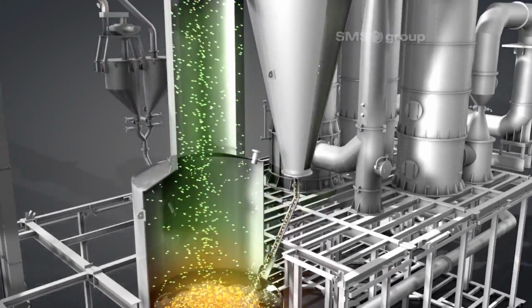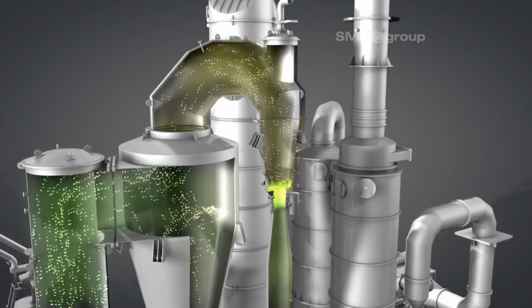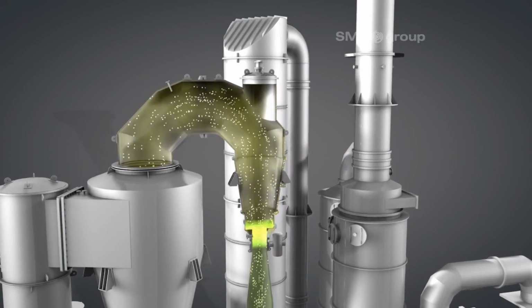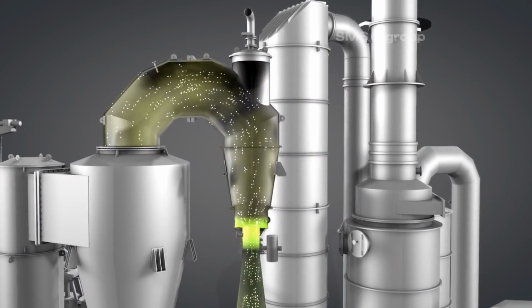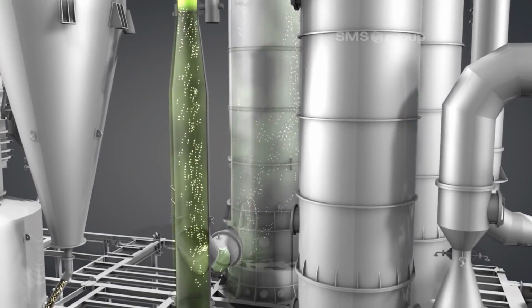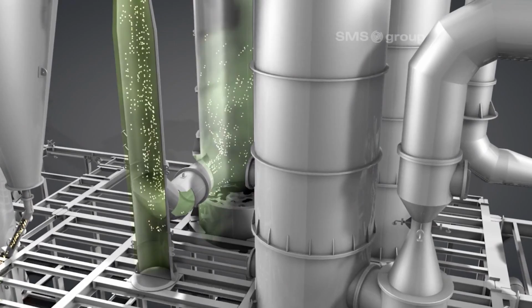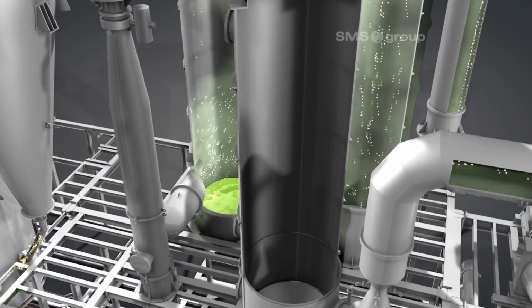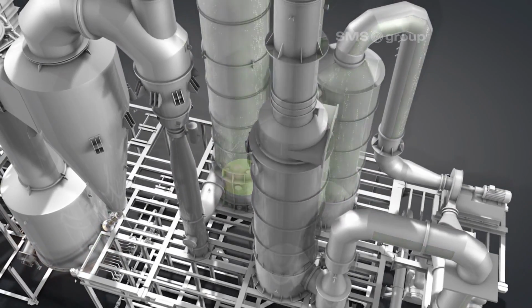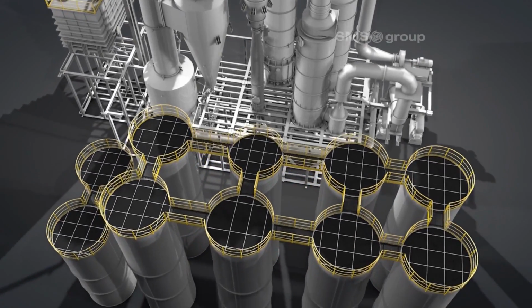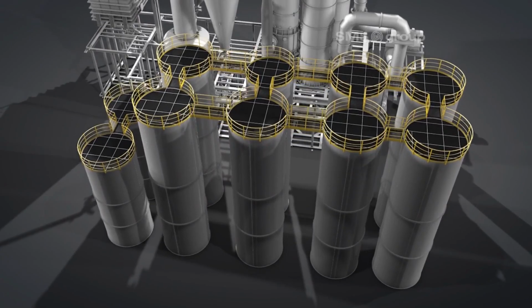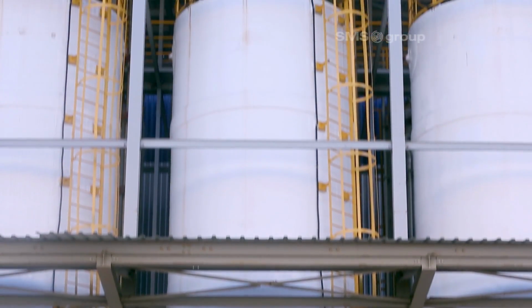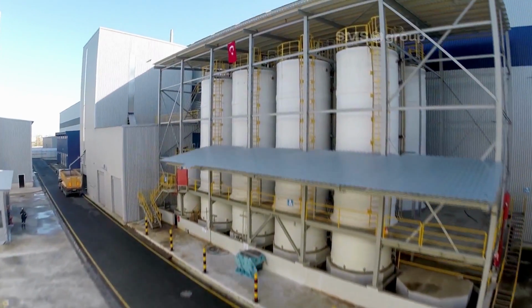The waste gas arising in the fluidized bed furnace is cooled in the Venturi evaporator. In the subsequent process stages, the hydrochloric acid gas is washed out by means of rinsing water. The regenerated hydrochloric acid accumulates in the so-called sump of the absorption column. The regenerated acid is stored in a tank group. An acid reserve is kept here to ensure high availability for the entire pickling line for 72 hours. With the capacity expansion, GAZİ will be obtaining a second recovery plant.